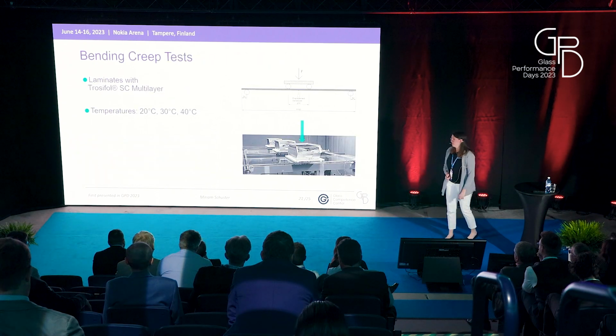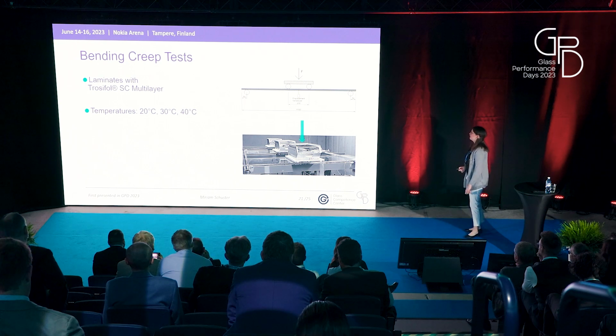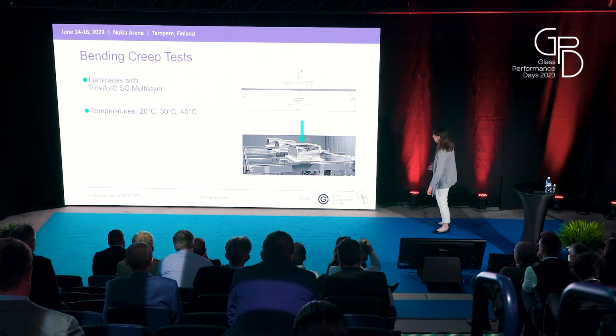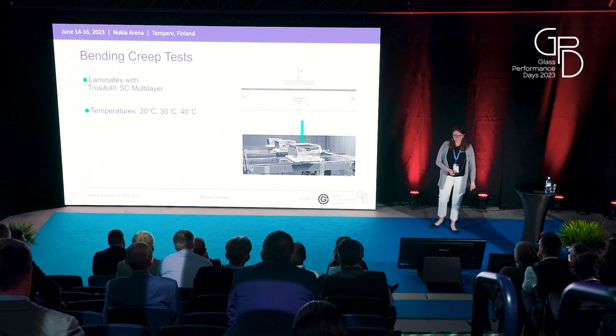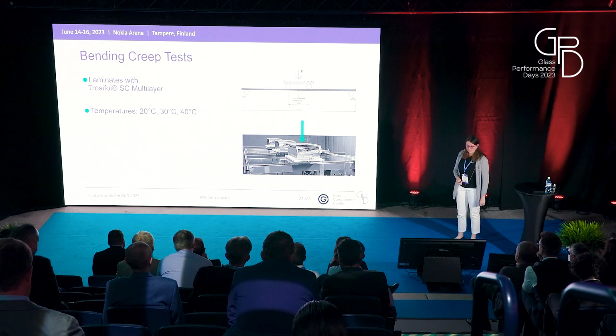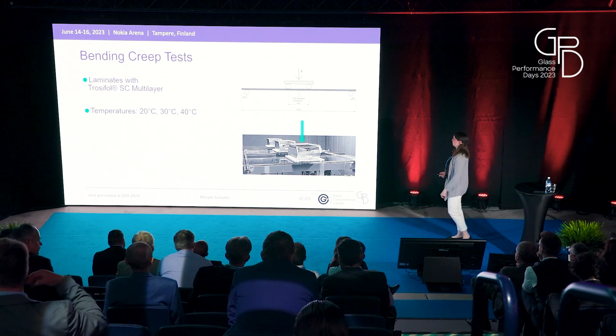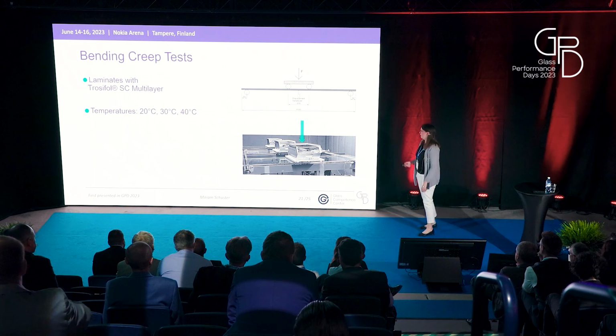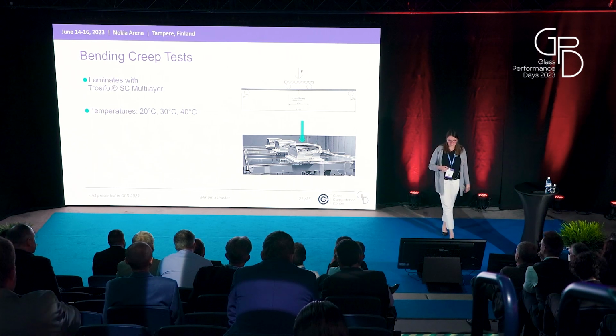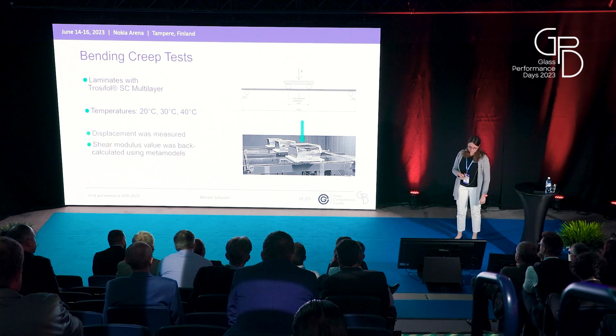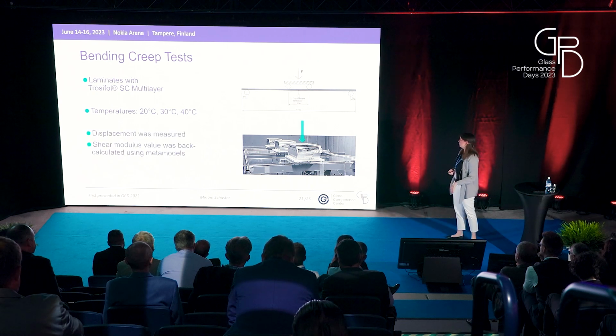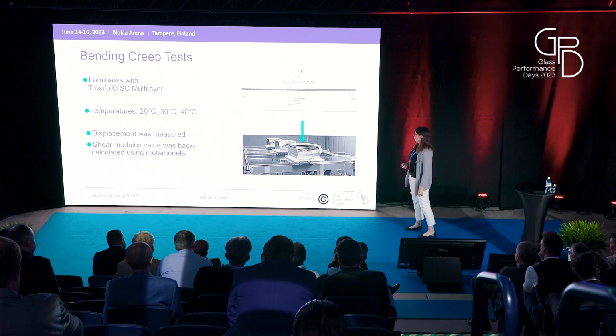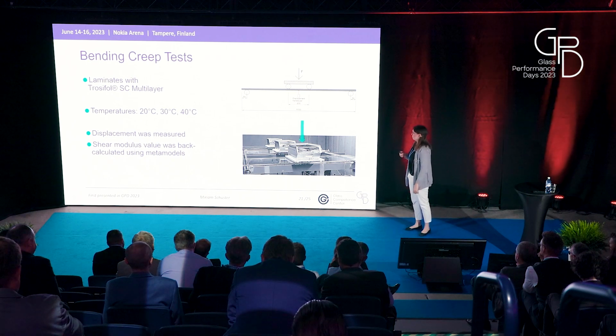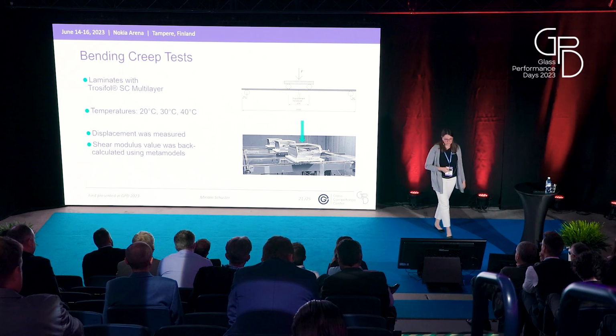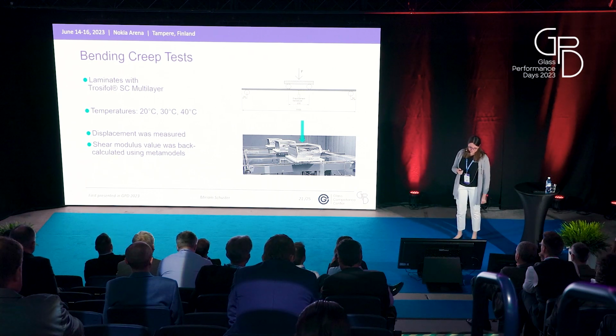Okay, then when we completed the DMTA test, also creep tests were done. They have been done at the University of the German Armed Forces and at Fraunhofer at different temperature levels, so 20 degrees Celsius, 30 degrees Celsius, and 40 degrees Celsius. And here only the multilayer was tested, not the individual layers. So what was done? A load was applied for a certain time. The displacement was measured, and from the measured displacement, the shear modulus was back calculated using some metamodels.